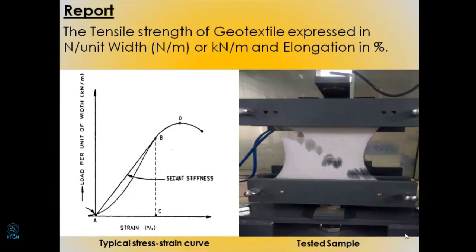We should be very careful while testing that the sample should not fail from the edge of the jaws, or it should not slip. If it is slipping or failing from the jaw, nearby the jaw, then we have to discard the test and we have to retest again.